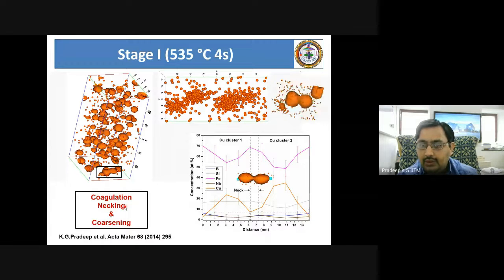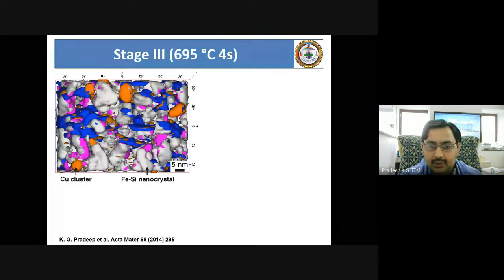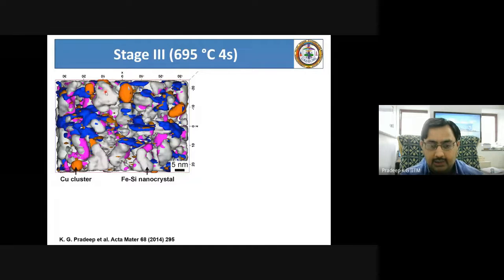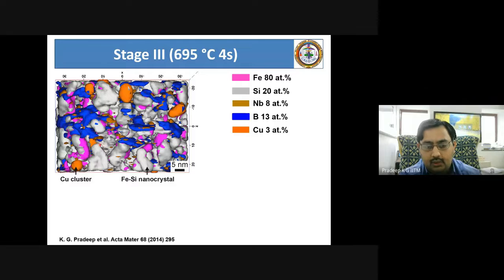But if you go to a later stage of annealing, let's say at 695 degrees for 4 seconds, now you can discretize the entire three-dimensional atom probe data set using concentration thresholds. That means all the iron silicon rich nanocrystals can be identified in the silvery color with the 20% threshold concentration of silicon. The copper clusters can be identified with a concentration threshold of 3%, so you can see this one. And the remaining elements, boron and niobium, form part of the rest of the amorphous matrix.